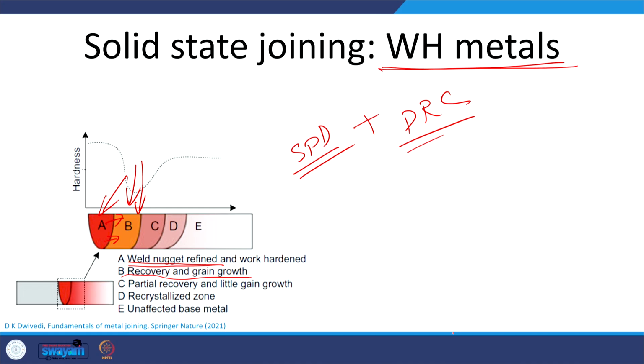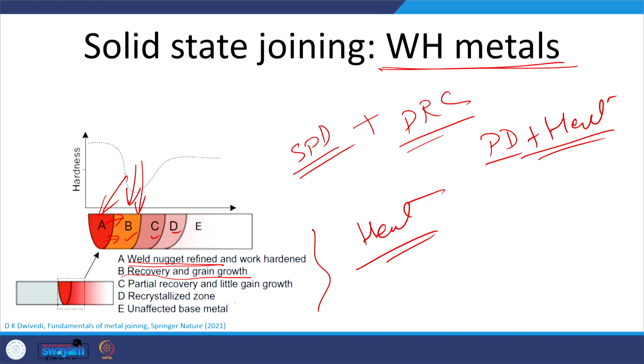hardenable metals. Likewise, all these zones B, C, D are being formed primarily due to the heat generated, while zone A is affected by the plastic deformation coupled with the heat both. Other areas like B will be affected significantly by recovery and grain growth, that is why we get the HAZ softening. That recovery will be partial a little away from the nugget area, coupled with a little grain growth, and then the recrystallization zone and the unaffected base metal. So, this is about the phase transformation or metallurgical aspects related with the WH metals.